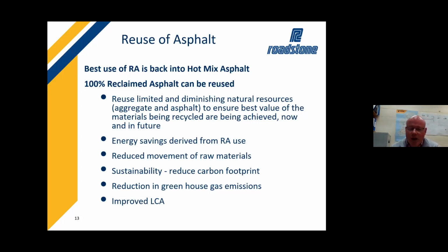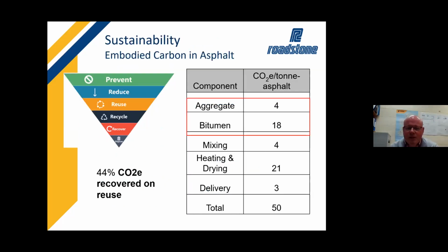Through this, we're going to have an improved LCA for these products. We're going to reduce our greenhouse gases. Now, in your ton of asphalt, we just did a calculation on your CO2 equivalent kgs per ton, and the two things that you're saving on when you're reusing reclaimed asphalt are the aggregate amount and the bitumen amount. You can't recover the mixing, you can't recover the heat nor drying. Those things are lost essentially, but because you use the aggregate and bitumen again appropriately, you will of course regain those, and that's recovering it.